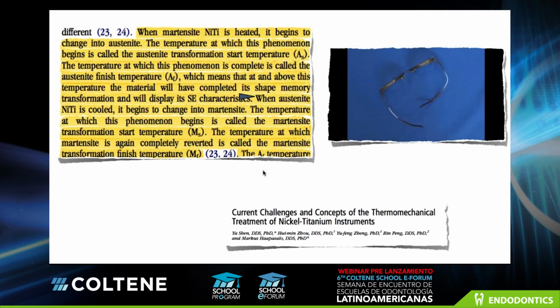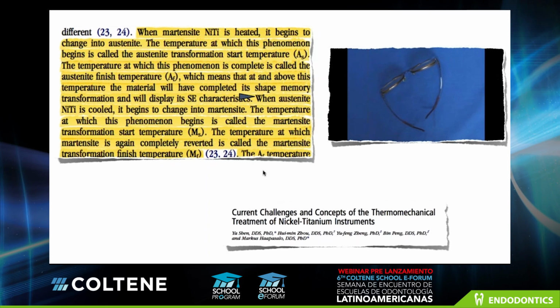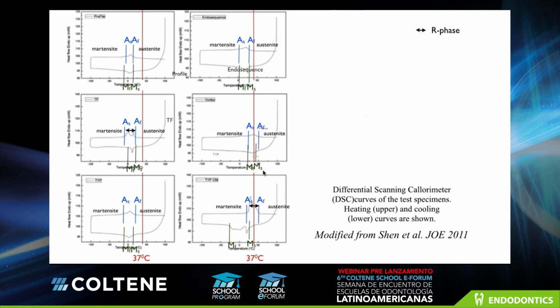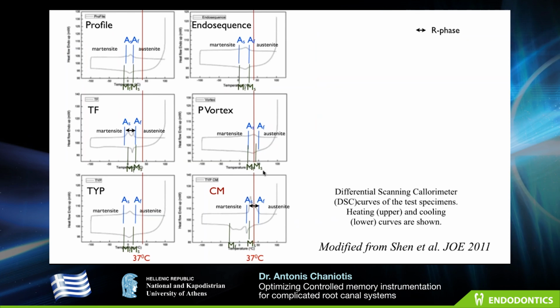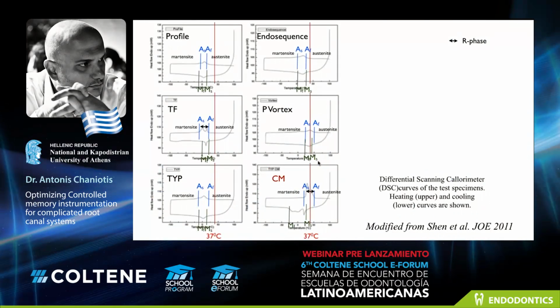The temperature at which this phenomenon begins is called the austenite transformation start temperature, and the temperature at which this phenomenon is completed is called the austenite finish temperature, which means that at and above this temperature, the material will have completed its shape memory transformation and will display superelastic characteristics. The different temperature-related phase transformations of nickel-titanium alloys can be studied effectively by using these differential scanning calorimeter curves. In this graph, a bit modified by Shen and colleagues, you can clearly see that different nickel-titanium instruments have different austenitic finish and martensitic finish temperatures.